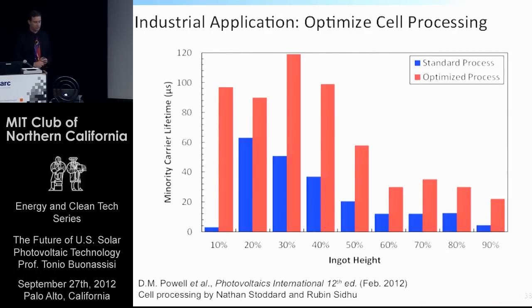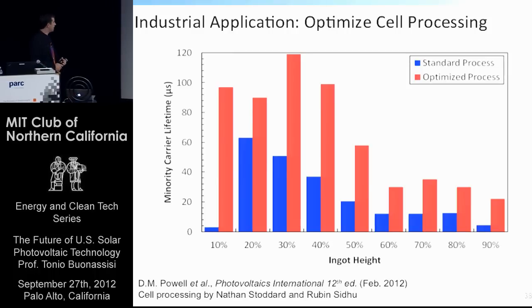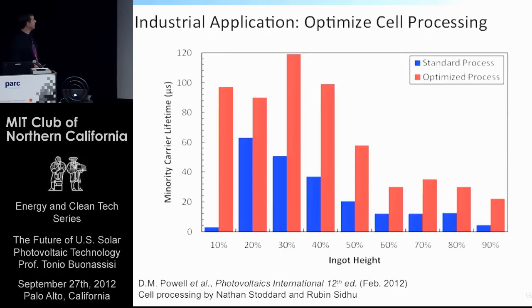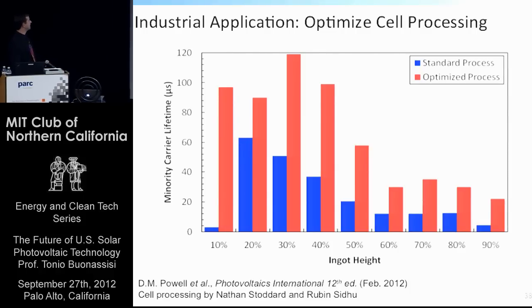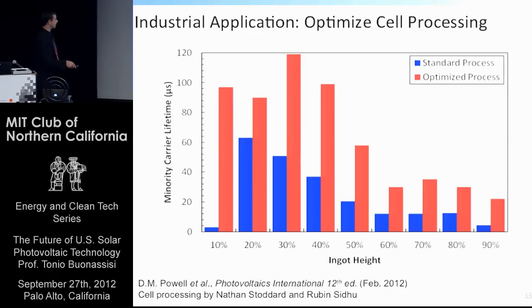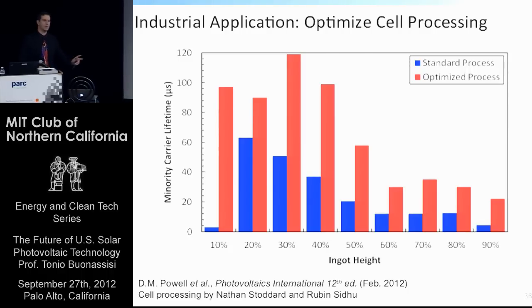But I'll jump to this, which is an industrial application of some of the earliest work within a multicrystalline silicon ingot. Unfortunately, the company that did the work with us is no longer here in the United States manufacturing. That's one of the casualties of the recent industry shakeout. But the principle remains, and it's used industrially in other companies. What's shown here is the standard process in blue. This is minority carrier lifetime, the electrical quality of the material. And the optimized process, shown in red here. And what you see is not only an improvement across the vast majority of the ingot, this is the ingot height, but you also recover material that you would otherwise throw away. That material at the very bottom of the ingot used to be so contaminated you could just chuck it.